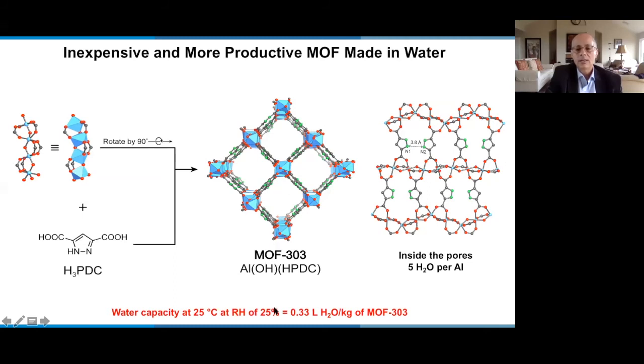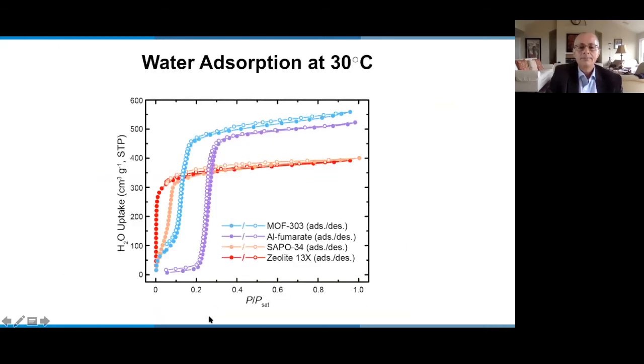It turns out that in the laboratory, this MOF takes up 0.33 liters, or 330 milliliters, of water per kilo of MOF at low humidity levels. You can see MOF 303 in comparison with other materials. MOF 303 is here in blue. It takes up water at very low humidity and it has a very high capacity. As I said, the zeolites and the other materials do not do well in terms of kinetics or capacity.